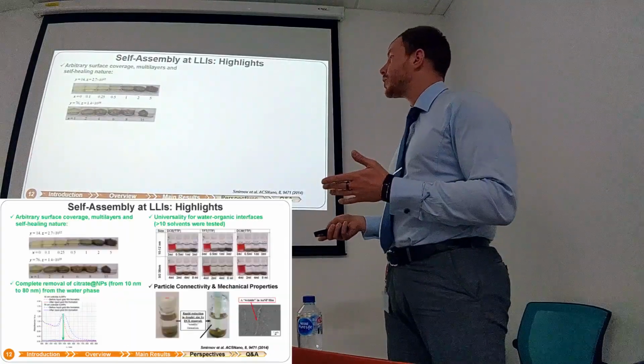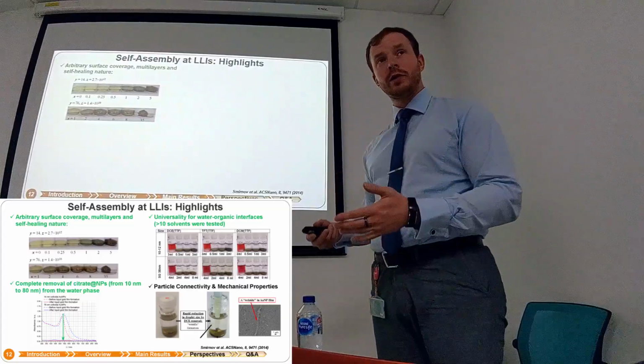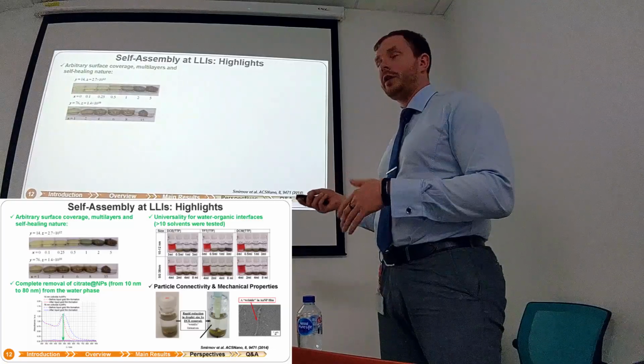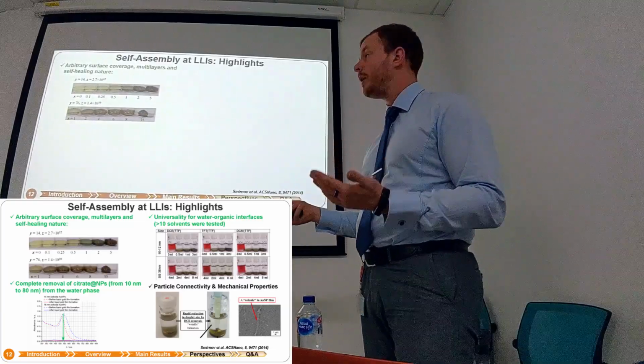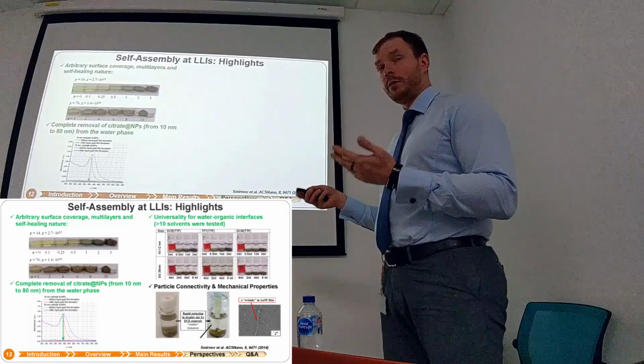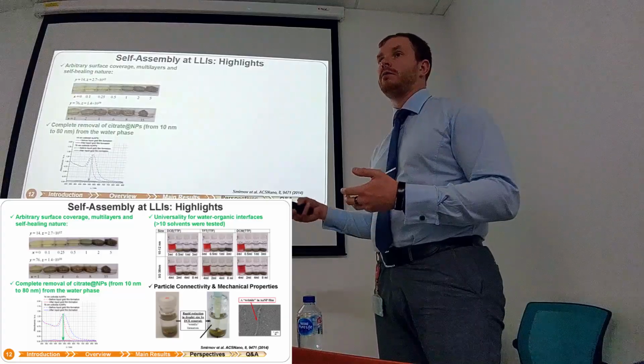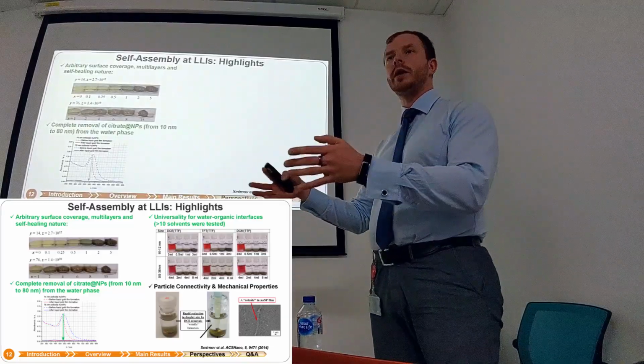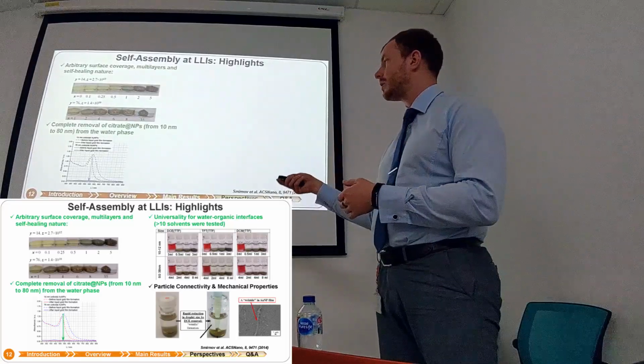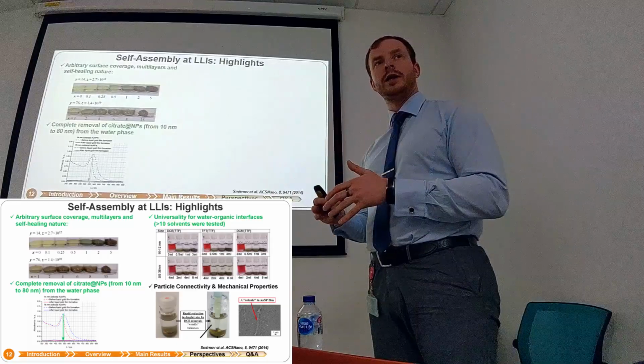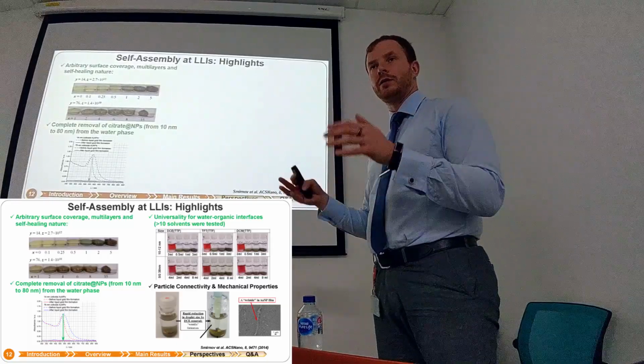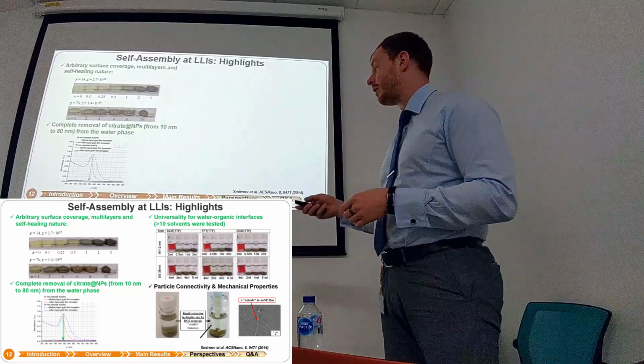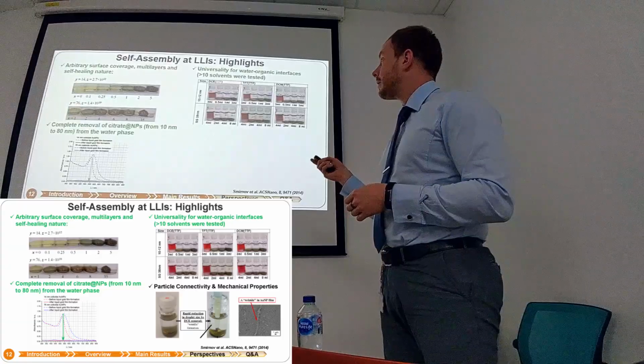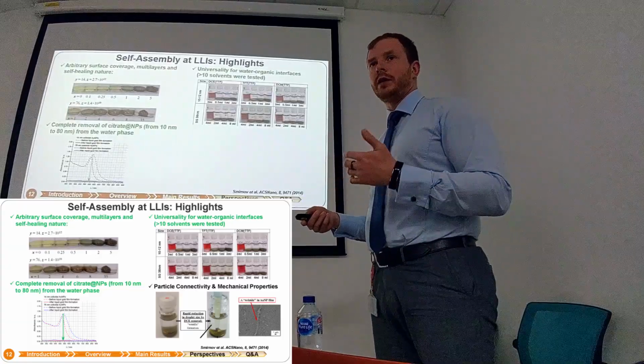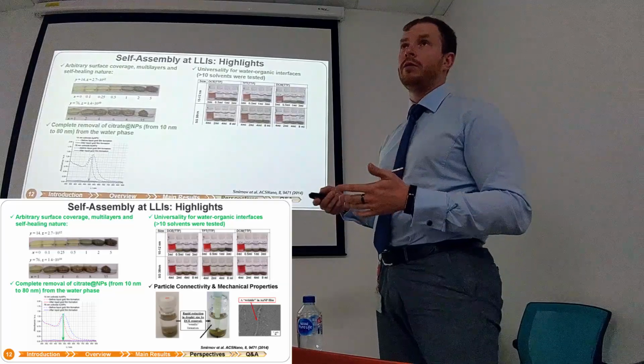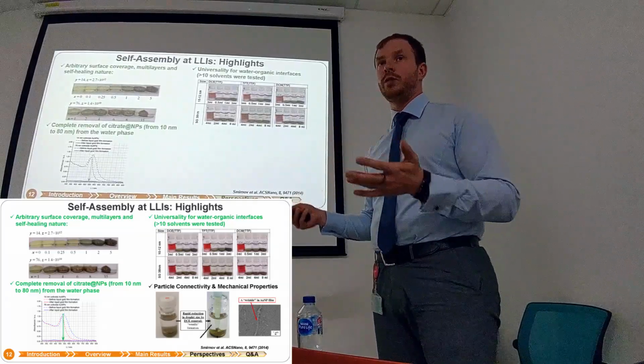Okay, fair enough. We showed that we can control the amount that we adsorb, so we can go very, very high and form even a multi-layer film. We showed that we can do complete removal of nanoparticles, meaning that, for example, from electronic waste we can create a nanoparticle solution, and then with this process assemble them and take every gold atom out of the solution. And this process is kind of universal. We tested it with dozens of solvents, and for some solvents it works better, for some worse, but still it's working for many solvents.